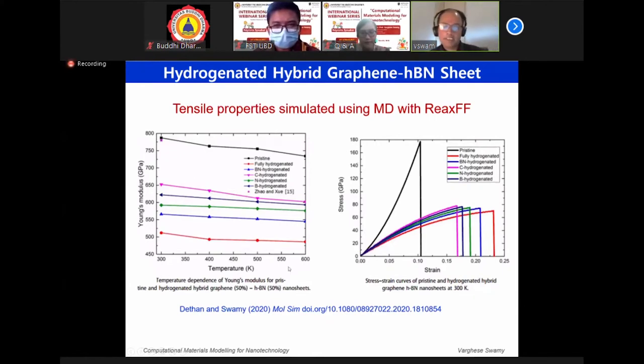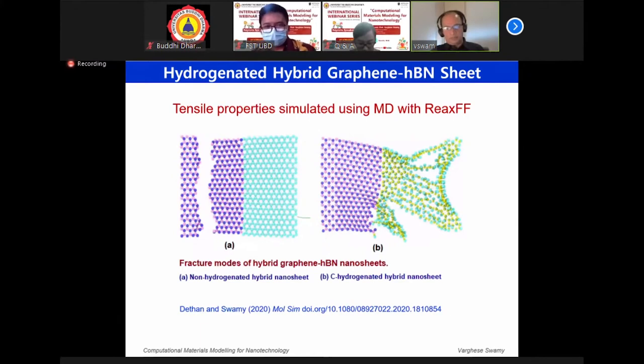If you look at the deformation behavior beyond elasticity, this curve here to the right, the first curve, shows the pristine material. It can withstand a stress of up to about 178 or 177 GPa before it fractures. So that's the fracture stress. Once you hydrogenate, in different ways or different configurations, you can see that the fracture stress is dropped by more than half. Depending on the type of hydrogenation, you can get different fracture stress or ability to withstand fracture in these materials. These properties are useful when we are talking about using such hybrid materials in applications such as nano-electromechanical systems or electronics, etc. We need to know how the fundamental properties vary.